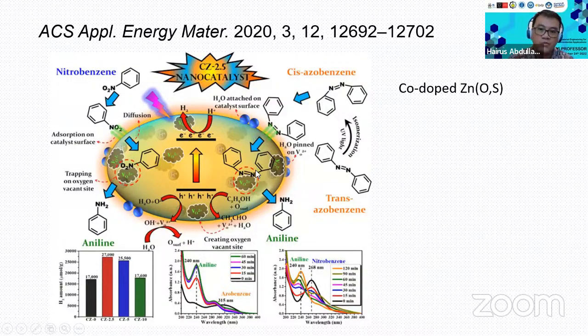So this is a very promising material, as we can do two kinds of applications together, like hydrogen evolution reaction and chemical conversion. This is a very green process because we just use light and the powder, and we add the chemical into the reactor. Then we have the product after the reaction, and it can also evolve hydrogen during the reaction. And this is the proof that we can see from the UV-visible: azobenzene changes to aniline, and nitrophenol also changes to aniline during the reaction.